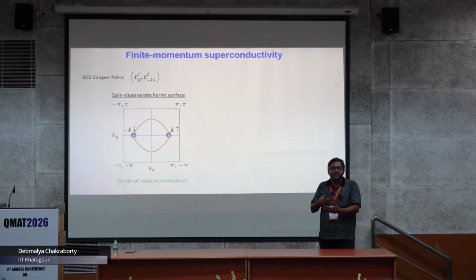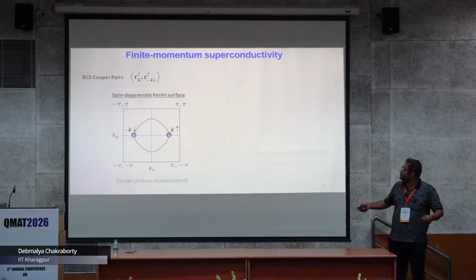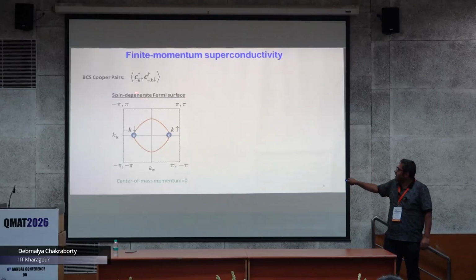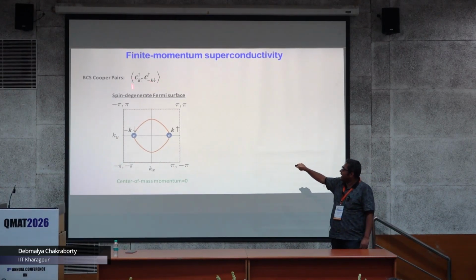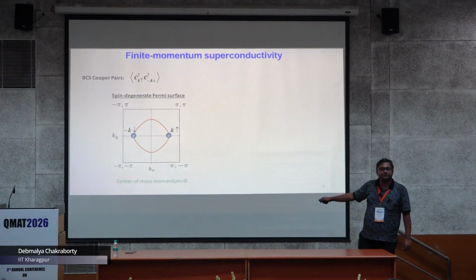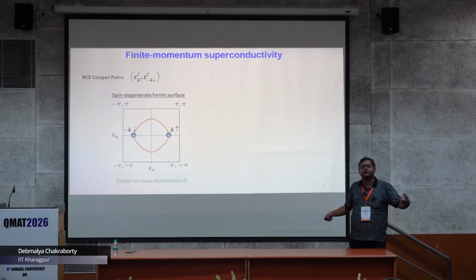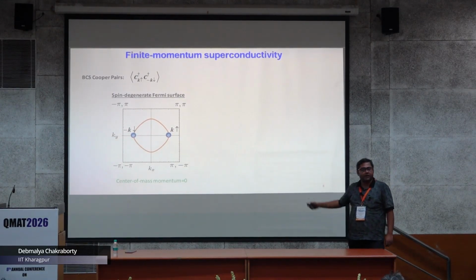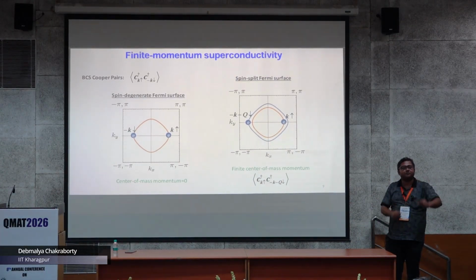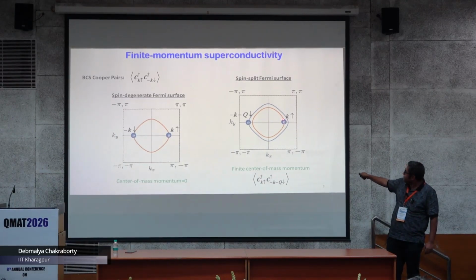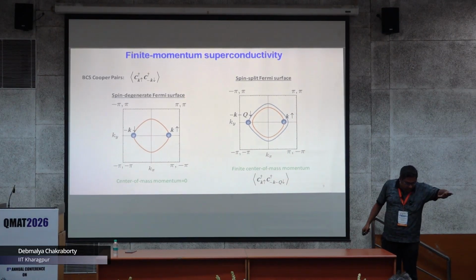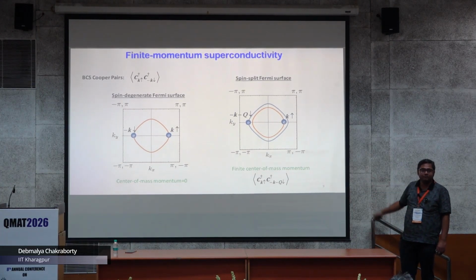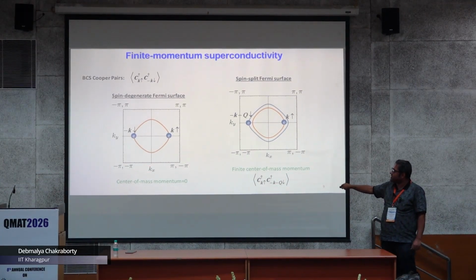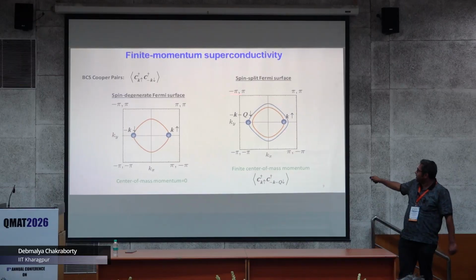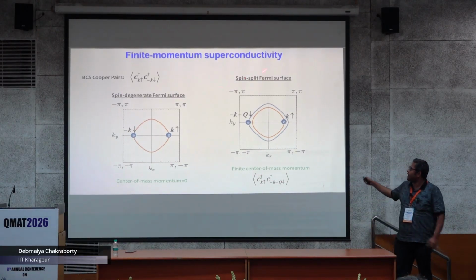Now in the presence of spin splitting, as Professor Singh mentioned, you can get something called finite momentum superconductivity. So let me mention it again: usual BCS Cooper pairs are made of k up and minus k down. That means if this is a spin degenerate Fermi surface, this is a k up. If I want to pair this with another electron minus k down, I will have one here. Now if the spin Fermi surfaces are split, this is the up one and this is the down one. If I want to find a minus k down, I will not find one, because this is only the up spin. As a result, the equal energy point would be somewhere shifted, which would be minus k minus q. While in the usual BCS case, the center of mass momentum, k plus minus k, is 0. Here the net momentum is q or minus q. That's why we call it finite momentum superconductivity.